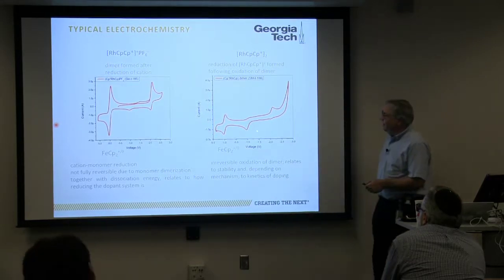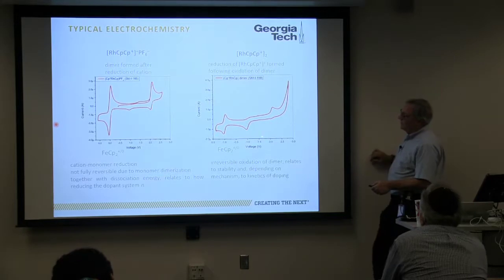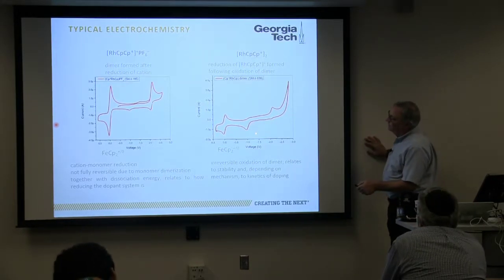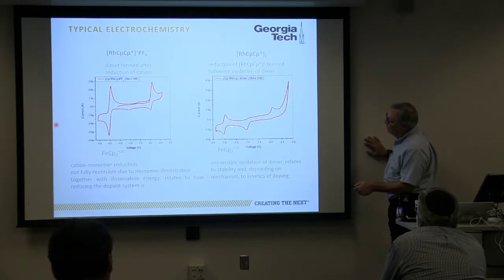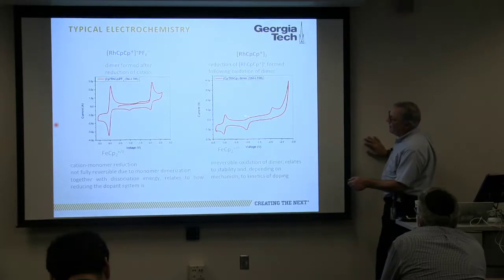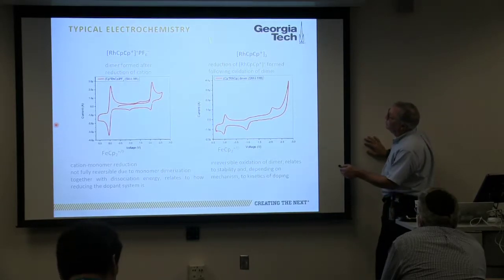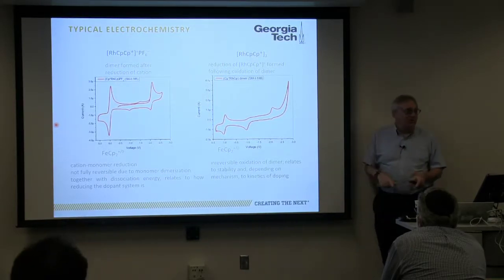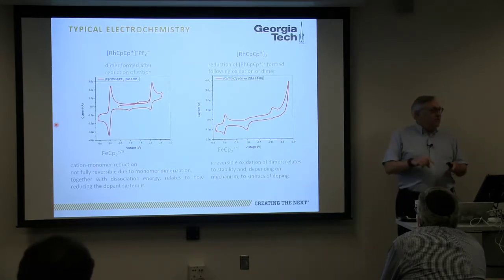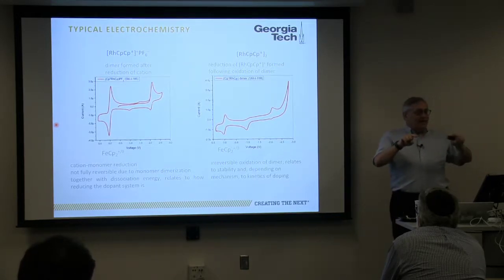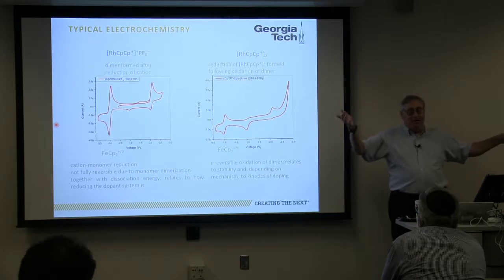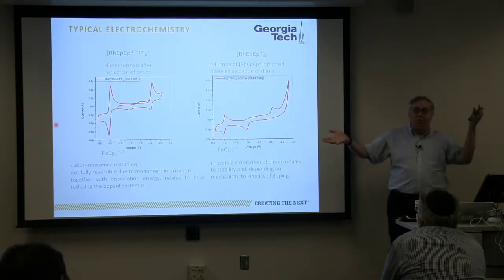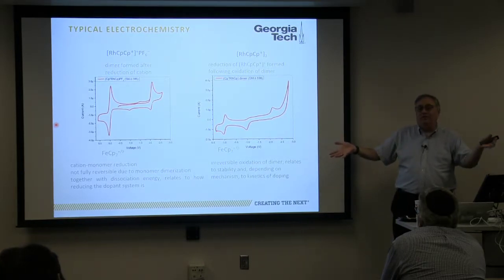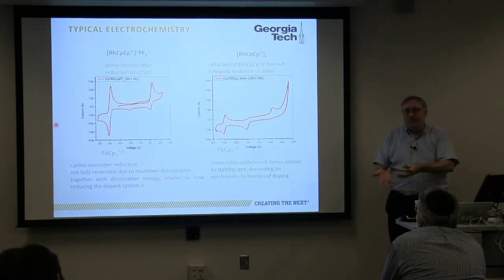Now, the other thing which we noted and had not really considered is that if you start with the dimer and you oxidize it, and this is just a standard internal standard, when you come back, you don't see the reverse wave of the cation of the dimer. What happens is once you take one electron out of this thing, it falls apart. And you get one equivalent of a cation and one equivalent of a very, very reducing material that itself